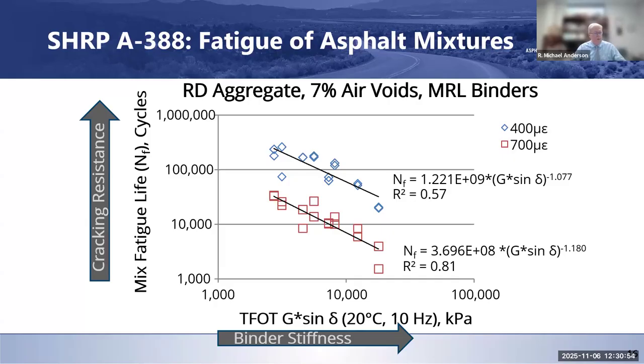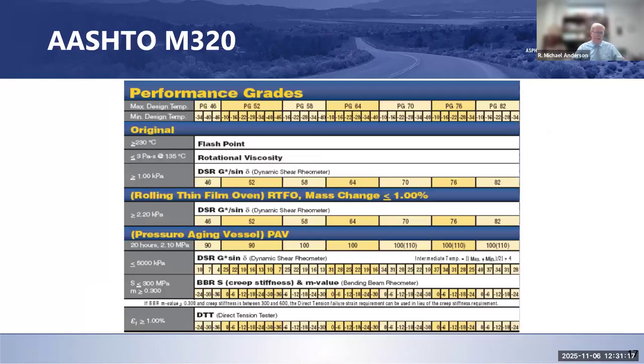So both of them have a role to play. I don't show the 4% air voids in here, but obviously that has a role to play as well. So all of them do matter. Not just the stiffness of the binder, but air voids matter. The aggregate itself, the combination and the packing, matters, as well as the strain that you get within the mixture.